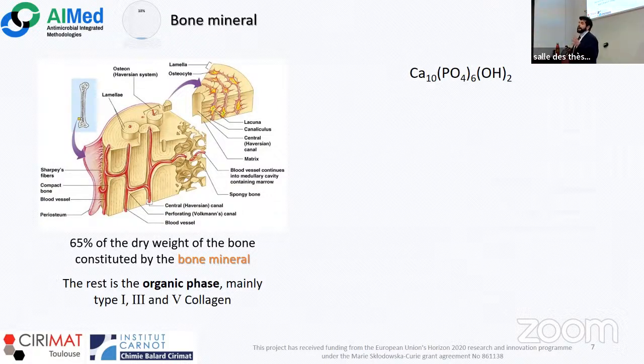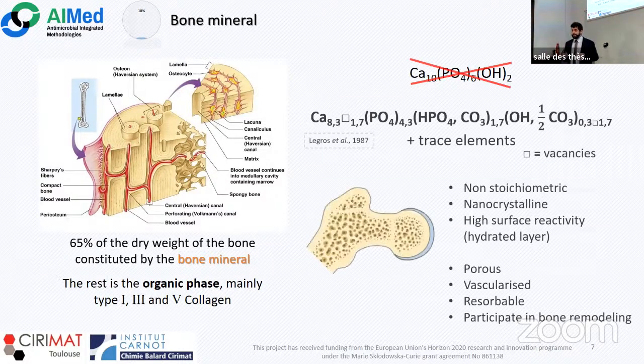The bone is composed for 65% of its dry weight of bone mineral. Generally it is considered to be stoichiometric hydroxyapatite, but as we know, and as was well explained by Legros in 1987, the real bone mineral is a bit more complex, and it is a highly substituted structure. This structure is also non-stoichiometric, it is nanocrystalline, and it has a high surface reactivity because of the hydrated layer that is present around these nanocrystals.